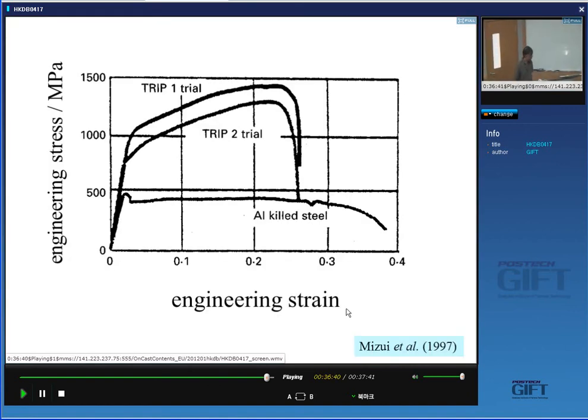And you can see that we get a high strength because we've got a mixture of hard and soft phase. Yeah? And you get continuous yielding, again because you've got a mixture of soft and hard. Because when you have a mixture of soft and hard, you have lots of free dislocations generated as soon as you start to deform it. So you don't get a yield point effect. A yield point effect is no good for formability. So much, much stronger than normal steels. And still you get a very respectable elongation from these steels.